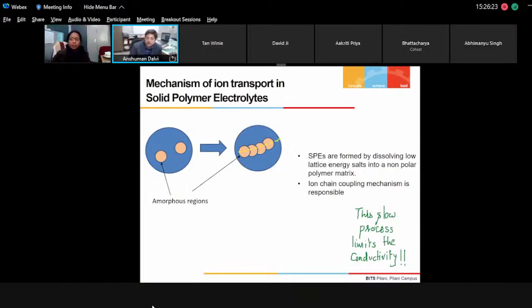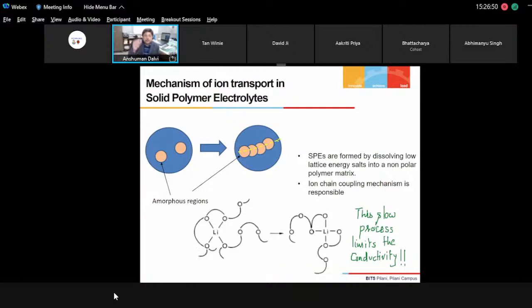And here you talk about the solid polymer electrolytes, about which in the 70s people started working on the theory behind SPE. So the salt, when it is dispersed inside a polymer matrix like polyethylene oxide, a high molecular weight polymer, then wherever the salt goes, you create domains of amorphous regions, and when these domains are connected to each other, then the ionic motion begins. And ionic motion begins because there is an ether oxygen with which the lithium ions couple, and this coupling, that means the ion chain coupling, is thought to be the real process of the electrical transport in these polymers. Now in the polymers you can see there is a flexible structure, there is space, but the process of electrical transport is slow because this coupling is the mechanism.